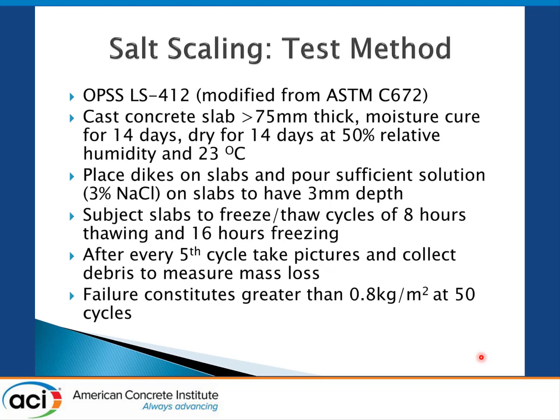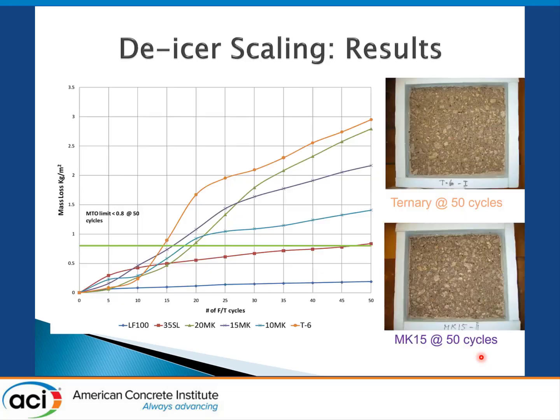Now, the other thing we do is de-icer salt scaling. And this is a modification of the ASTM salt scaling test. The main difference is that the OPS, the Ontario Provincial Standard our highway department uses, they use a 3% sodium chloride solution instead of the 4% calcium chloride solution that is used in the ASTM methodology. And they use a mass loss criterion of less than 0.8 kilos of mass loss at 50 cycles. Now, this test method has been problematic for concretes made with SCMs in the past, which is one of the reasons we developed a different Canadian standard test method.